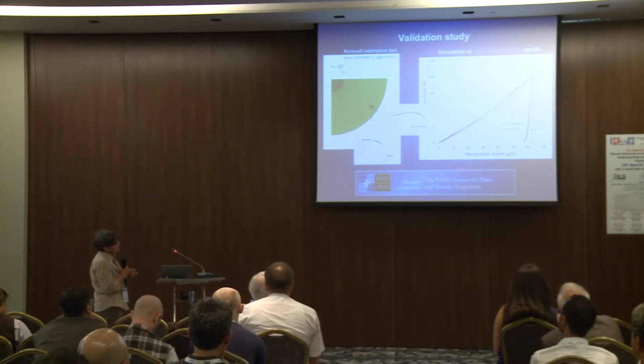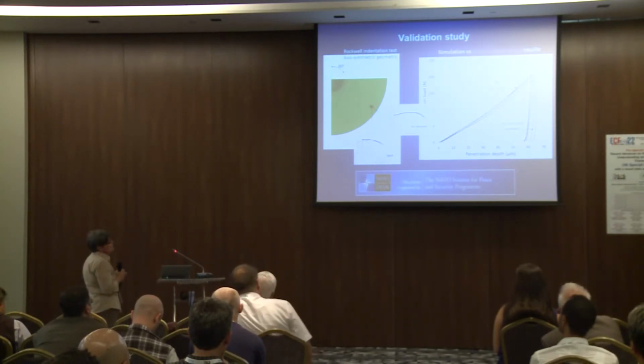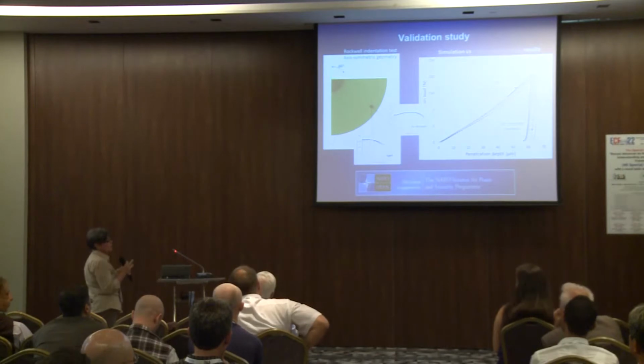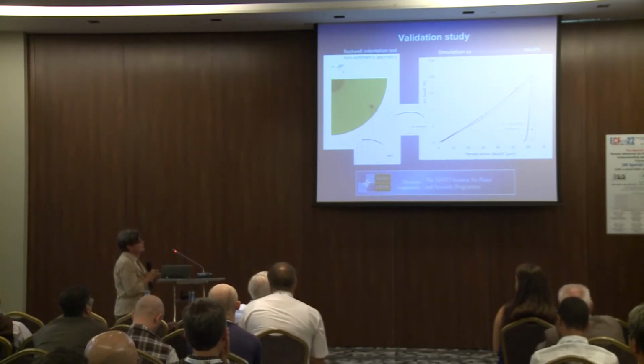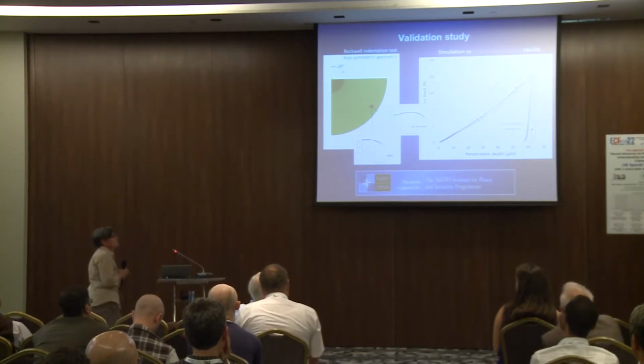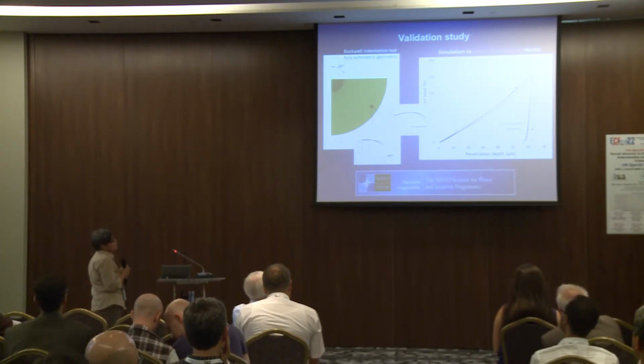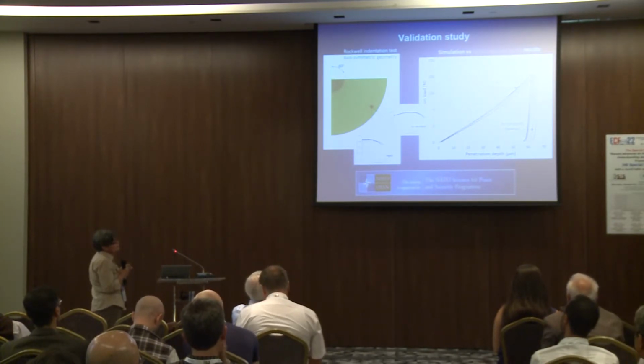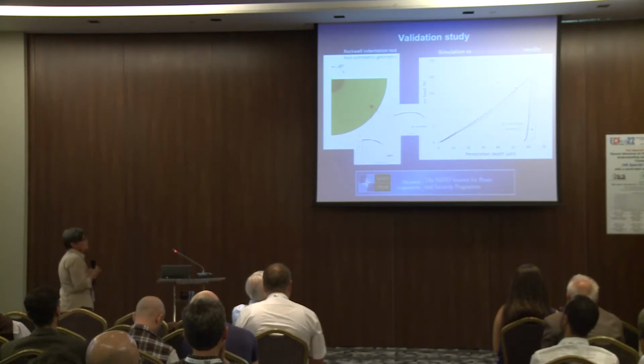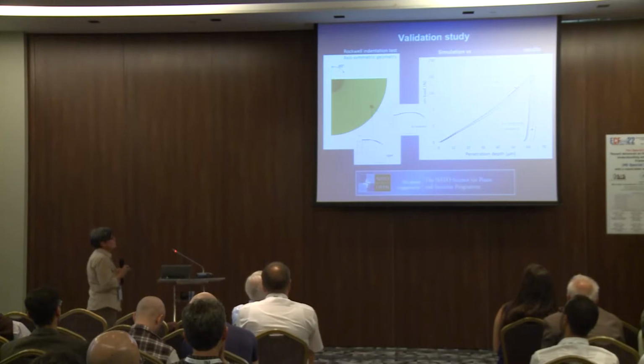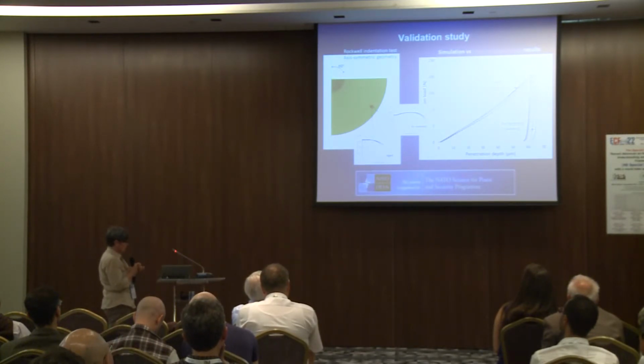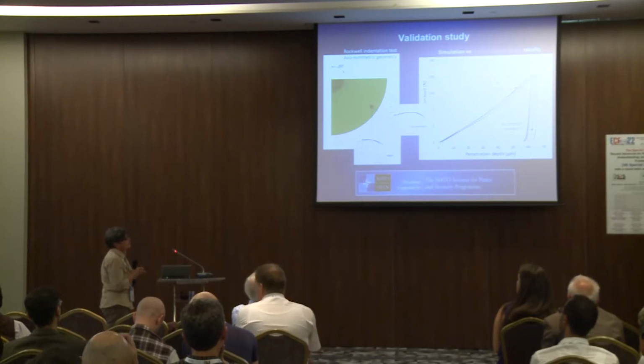What we see in this graph is the comparison between the mean experimental values, which are given by the blue curves, and the simulations, which are the black curves. What you can see is that there is a fairly good correspondence between the two, despite the fact that we are working at different scales, therefore confirming that this test, even at this relatively low level, 200 Newton maximum load, already gives information which is consistent with the bulk material properties that we can get from more sophisticated testing.